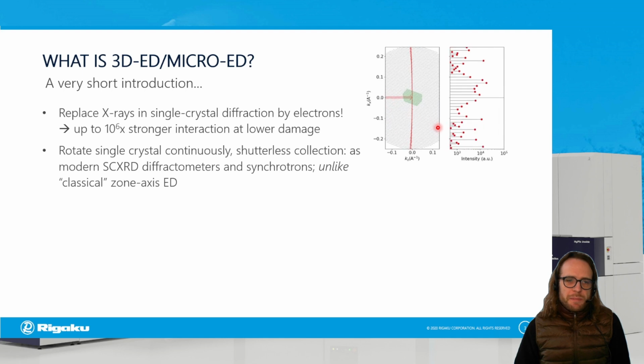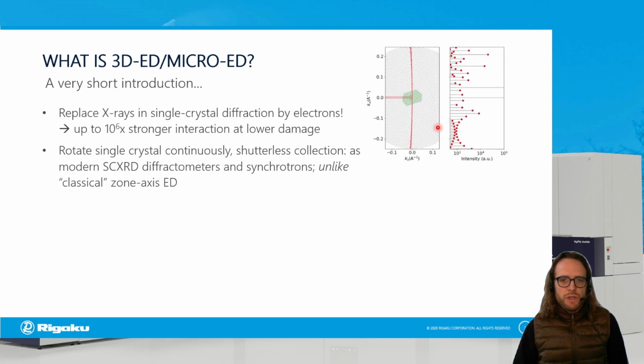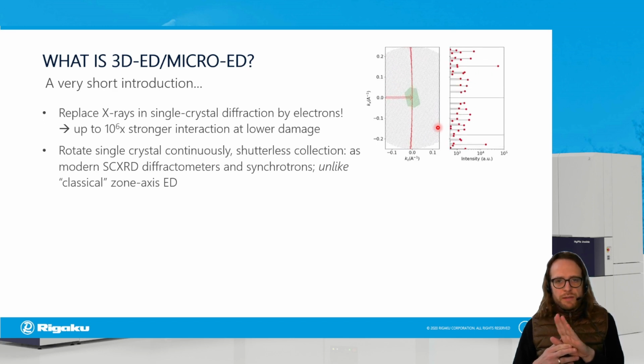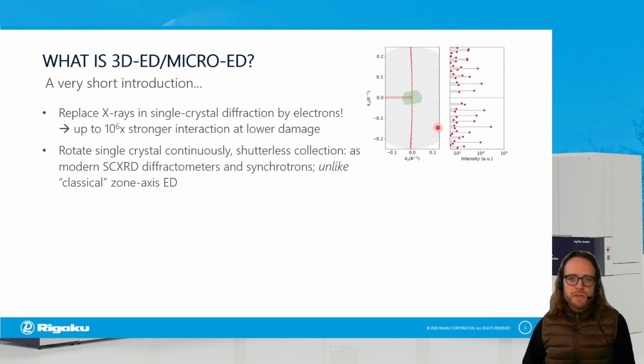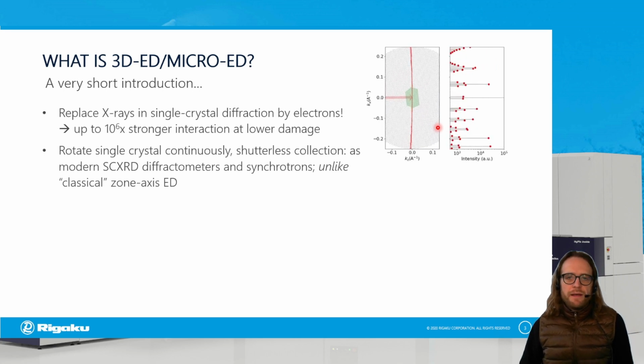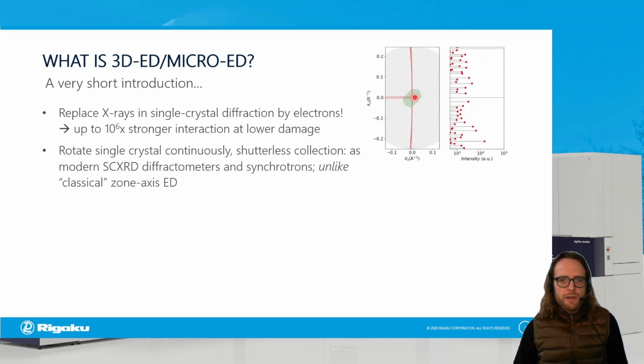peaks. What's important is that this is quite different from what electron microscopists classically call electron diffraction, which is where you tilt your sample to well-specified angles that coincide with low-lying zone axes of the crystal, and then take single micrographs. This is much more similar to X-ray data collection strategies, and can, in contrast to the latter, be used very well for structural characterization of any material.